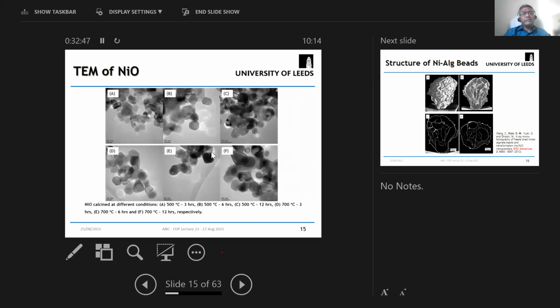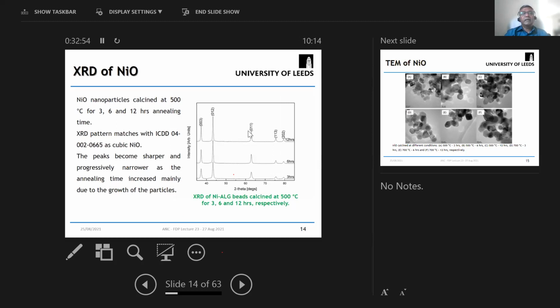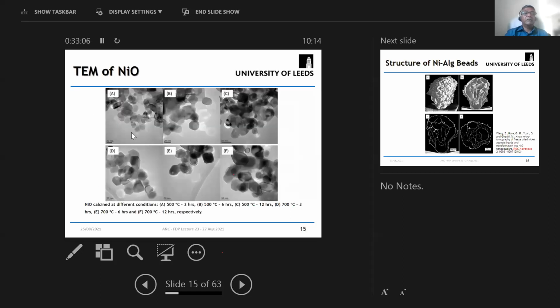These are TEM images. Even here, for example, they are still in nanoscale, but they are in the range of around 100 nanometer, whereas here they are in the range of about 10 nanometer to 20 nanometer. So you can see here, these are the TEM images of different nickel oxide particles produced by different thermal history. For example, A, B, and C are at 500 for 3, 6, and 12 hours calcination, whereas D, E, and F are at 700 degrees Celsius calcination for 3, 6, and 12 hours respectively.